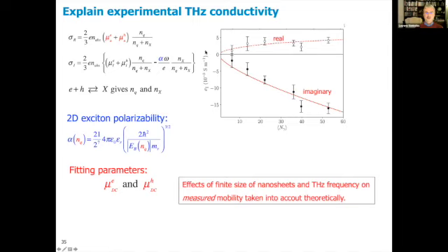Now, we calculated these curves to reproduce the real and imaginary conductivity as a function of the number of absorbed photons per nanosheet. So we have these expressions for the conductivity that I've shown you already. We calculated the 2D exciton polarizability for the ideal case of a hydrogenic model in 2D, but we use the exciton binding energy as a function of the number of free charges. So the exciton binding energy goes down when we are at a larger number of free charges or a higher number of absorbed photons per nanosheet.